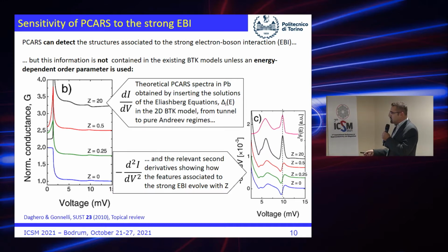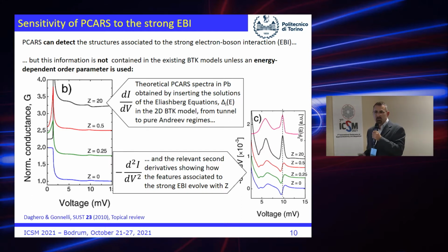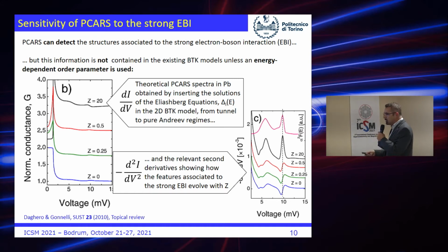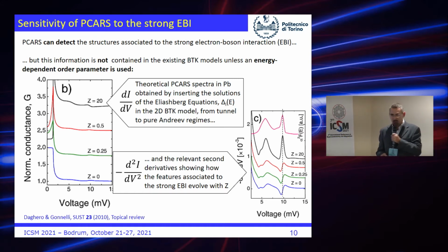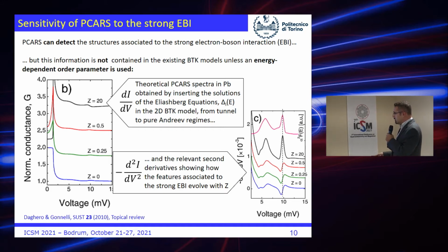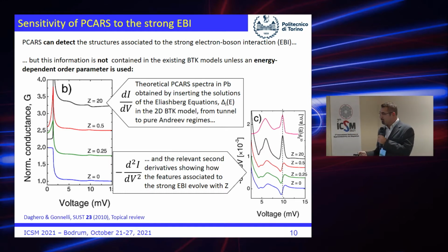But if you change the value of Z, you arrive even to Z equal to 0. You do not have a perfect correspondence, but at least you have structures, at least a peak, whose position more or less corresponds to the energy of the peak in the initial spectrum. So what we are doing now is exactly this. We start from curves that are in this regime, and we extract the information about the boson that is responsible for the pairing.